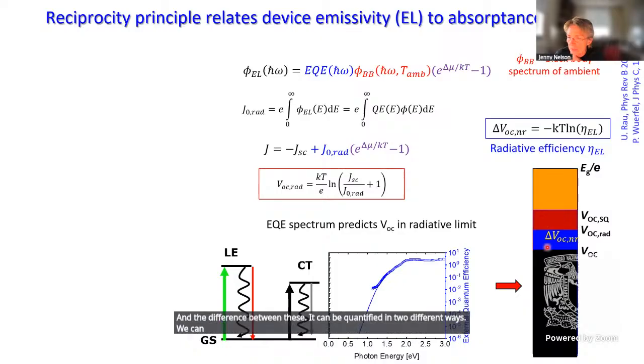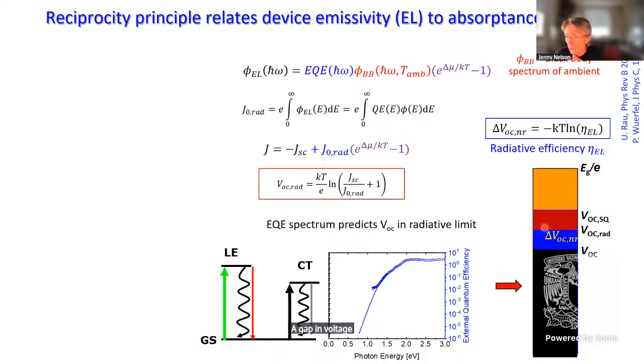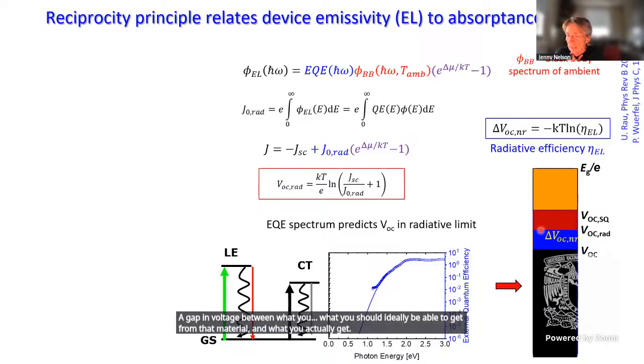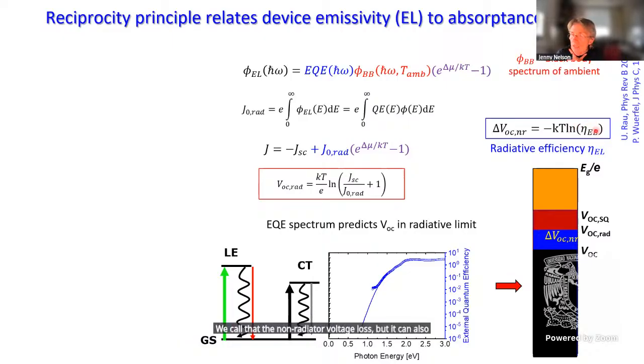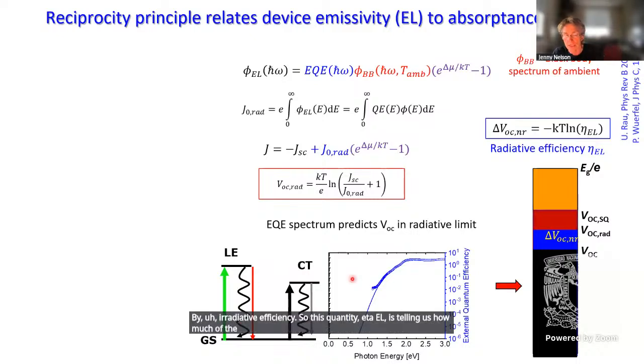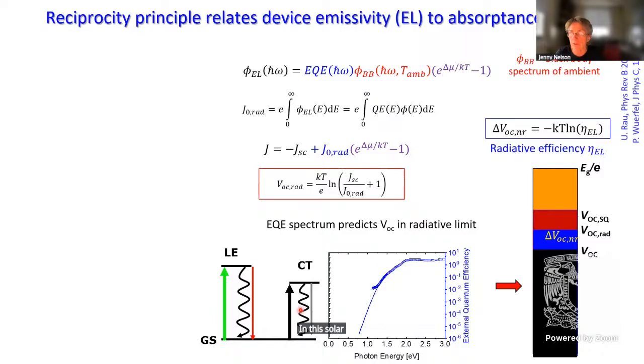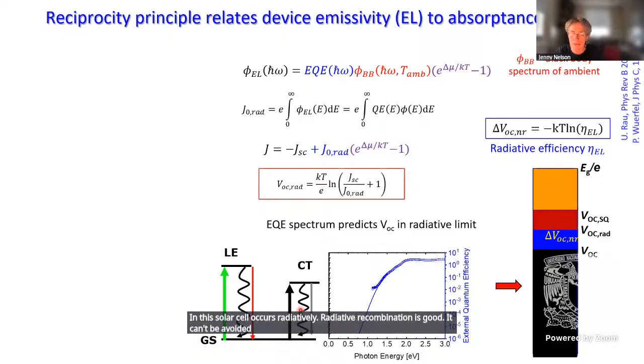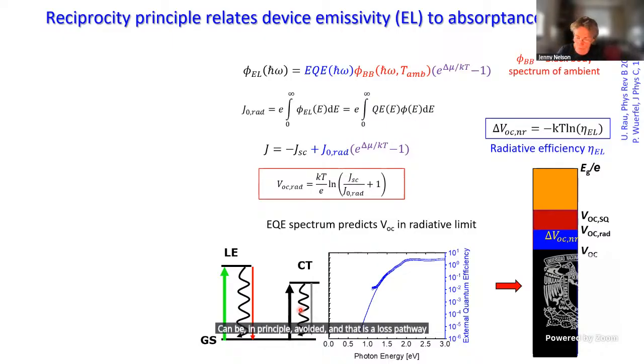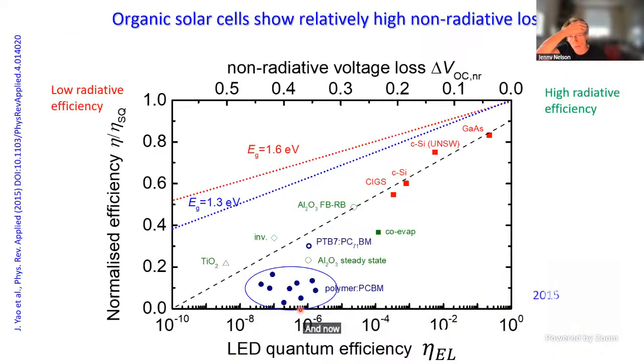We can quantify it as being a gap in voltage between what you should ideally be able to get from that material and what you actually get. We call that the non-radiative voltage loss, but it can also be quantified by a radiative efficiency. So this quantity, eta EL, is telling us how much of the recombination that occurs in this solar cell occurs radiatively. Radiative recombination is good, it can't be avoided, but non-radiative recombination can, in principle, be avoided, and that is a loss pathway that we want to avoid. Okay, so that's the end of the physics for the moment.